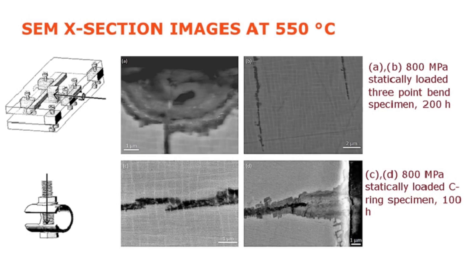If we have a look at a few cross-sectional images now, we can start to see how this mechanism is interacting a bit more with the microstructure. Image A, up on the top left, is showing what looks to be a bit like a corrosion pit, and we've got a crack which has initiated and propagated out the bottom of that pit. We obviously can't tell what came first, the pit or the crack, but we also see the corrosion interacting preferentially with the gamma prime, and this is backed up by the following images. We can see at the crack tip in image B, again, it's interacting with the gamma prime, propagating on orthogonal cube planes through the material, and even some bridging through the gamma. The gamma prime is typically the strengthening phase or precipitate. So preferentially oxidizing that is locally weakening the material and enabling this crack propagation.